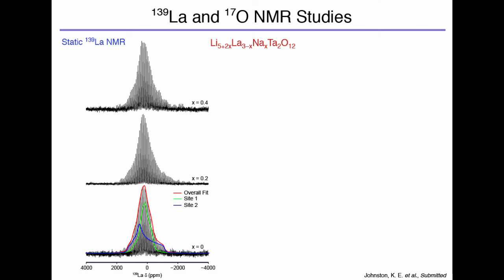It turns out if you look at the parent material, the 0.2 and the 0.4, they're basically the same. There's no change between them. What's more interesting is, in order to fit this line shape, you actually need two distinct lanthanum sites, not one, which is what we would predict from the diffraction data. So it looks like NMR is telling us something more than diffraction at this point.